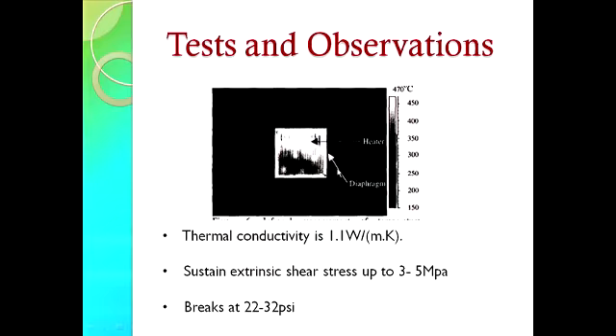in this process, this is the silicon dioxide. This is silicon dioxide ring, and inside it there is a heater. The dark portion shows a lower temperature and the white portion shows a higher temperature. So we can see that this silicon dioxide layer prevents the dissipation of heat to the outer surface. So this is a good insulation material.